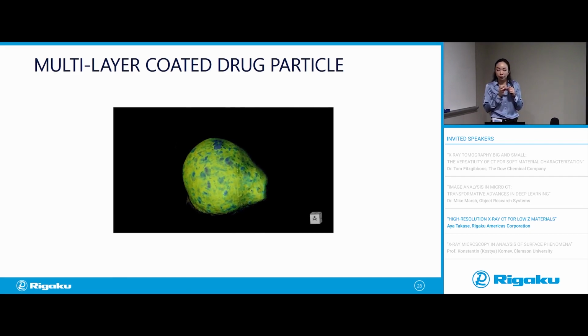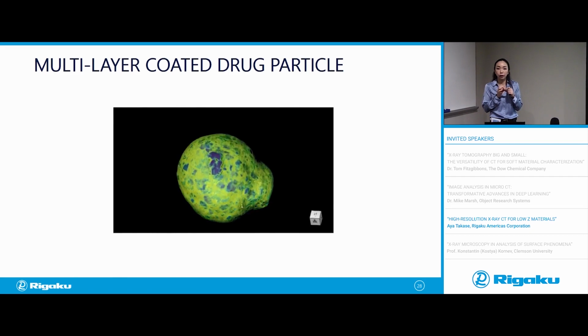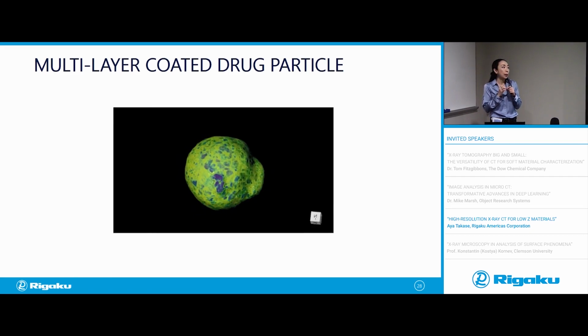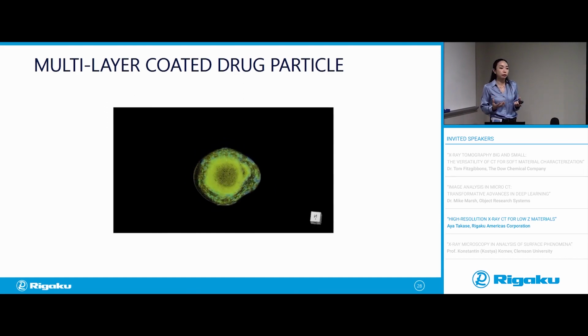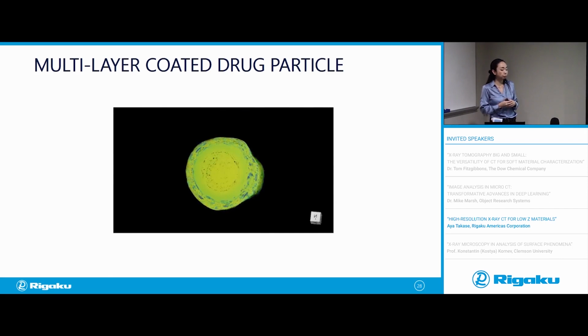And the whole thing is organic. It's tiny. There is not a lot of absorption of the X-rays by the sample. But you can see different coatings, different layers, different fillers in the surface layer. And you can analyze the coating thickness or void volume fraction, all those things, using software like Dragonfly.